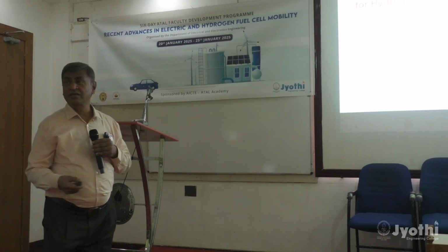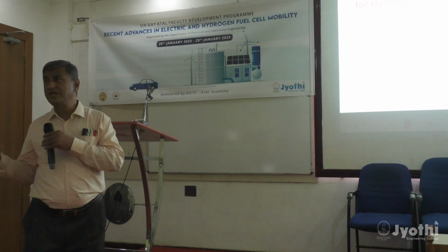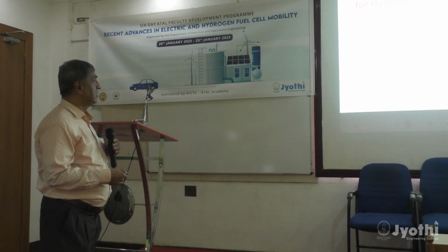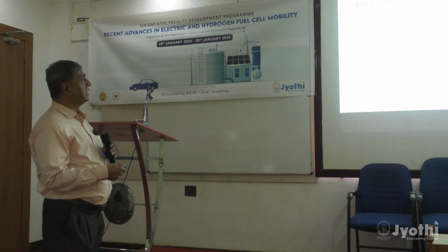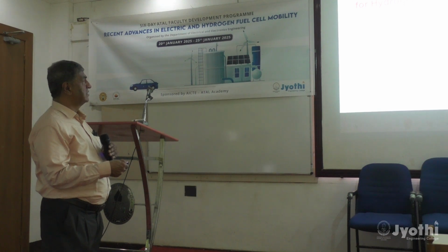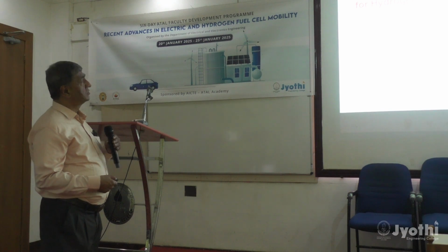As I mentioned, there are many such metal oxide catalysts like ceria or ferrous compounds, etc. At different temperatures, it is possible. So if a lot of heat is available from some source, it is possible to use these metal oxides. It's almost like a reversible reaction. Metal oxide gets reduced, and once again it gets oxidized when steam is passed, going back to its original state. In the process, some oxygen is evolved at some temperature, and at a slightly lower temperature, hydrogen is produced. So this process can be repeated back and forth.